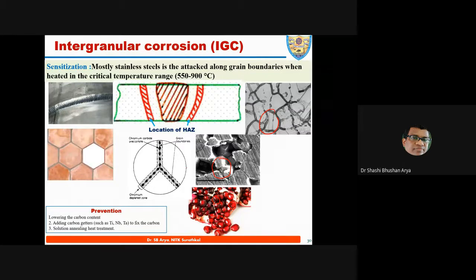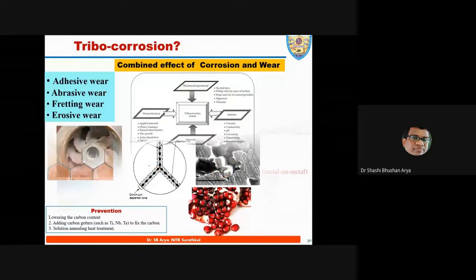When you do the stainless steel welding at this temperature, it is called sensitized material, stainless steel. Because chromium carbide will precipitate out and that will give you the high active area. This area becomes active, becomes anodic, and the rest of the area, the grains, become cathodic. And that is why failure will take place actually. Yeah, so that is the way.